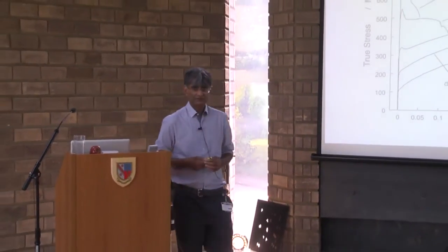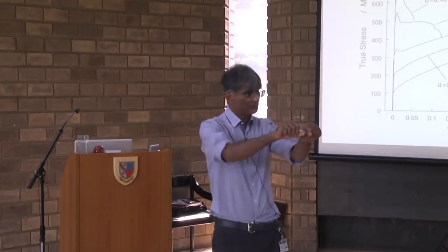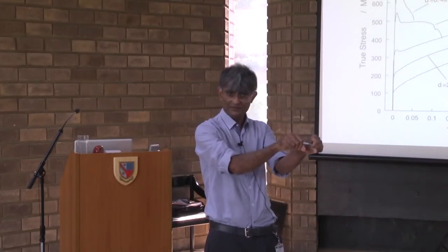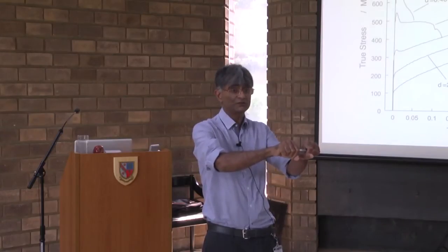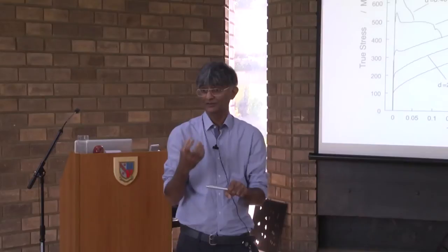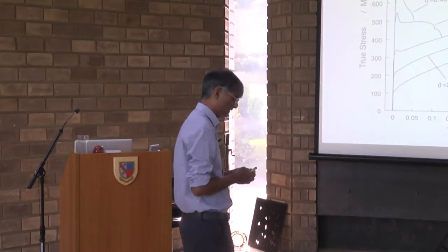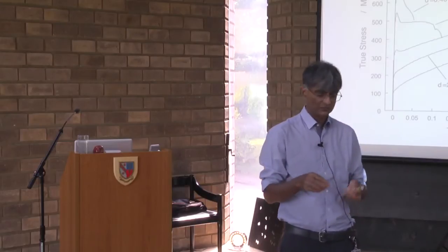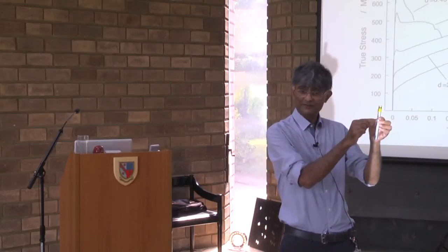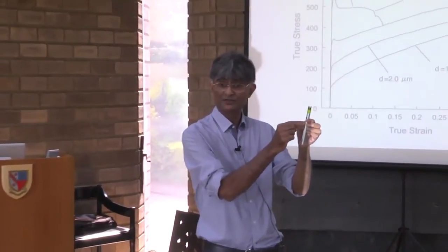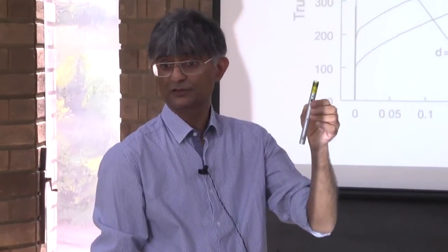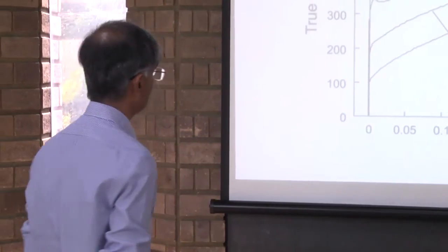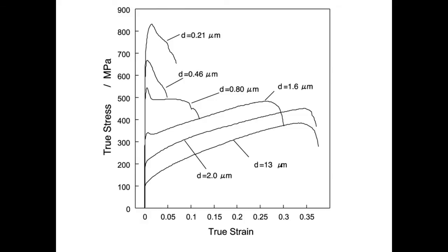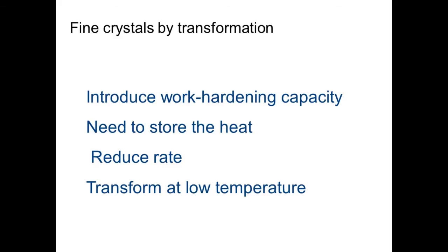There is one more difficulty. When you take a piece of metal and you bend it, the first time you bend it, it's easy. But if you try to unbend it, it's much more difficult. That's called work hardening. So the material actually becomes harder when you deform it. And that's a very good thing, because supposing I get a small defect here, the work hardening will strengthen that defect, and therefore you can get lots of elongation before fracture. Okay? So work hardening is an essential property. If you don't have it, you get a plastic instability immediately, and you lose your ductility. So we need a mechanism of work hardening in addition to all those requirements.